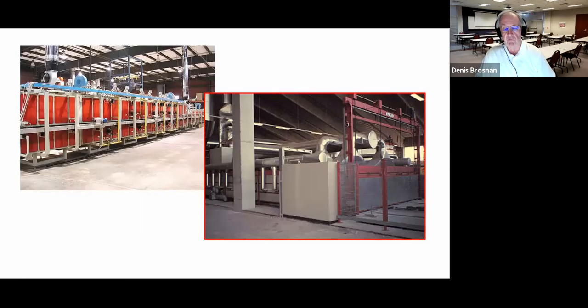Now here are a couple of continuous kilns. This is the roller hearth kiln in my laboratory. Individual ceramic rollers propel ceramic tiles, in this case, along the length of this kiln. They're one high, not stacked up, and they are heated up gradually. They get into the hot zone of the kiln where the highest temperatures are, and then they're cooled off. And so we can see the kiln stack in this end of the kiln.